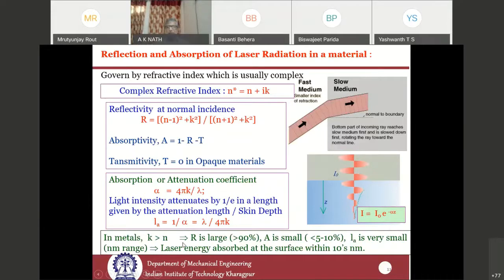In metal, the K value is usually large because there are a lot of free electrons available. Because of that, the reflectivity R tends to become almost 90% or close to 100%, and absorptivity, 1 minus R, becomes very, very small. The attenuation length is also very small, in the range of nanometers.